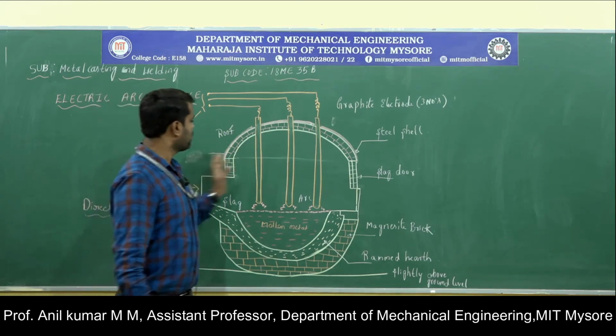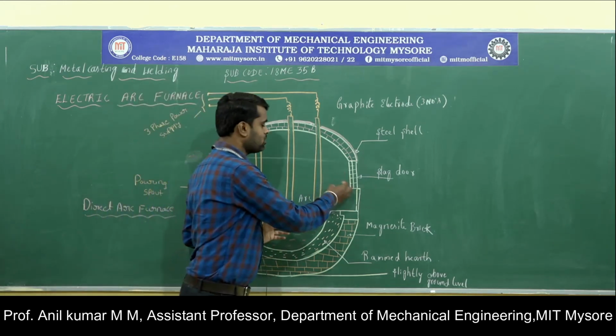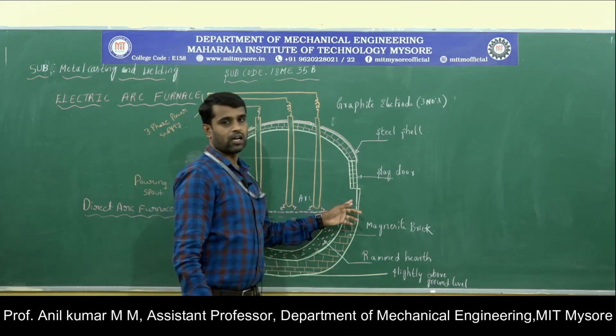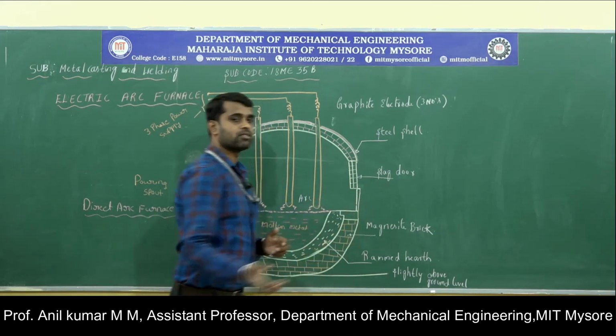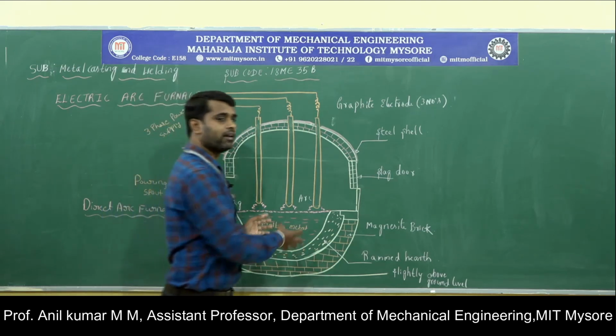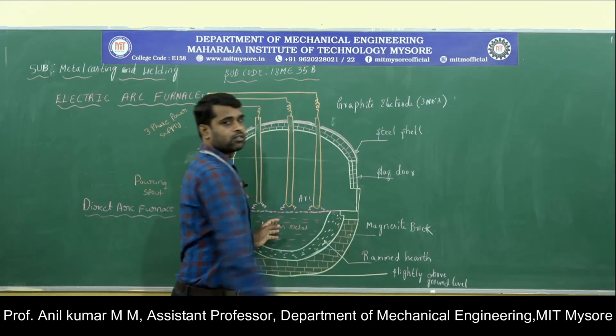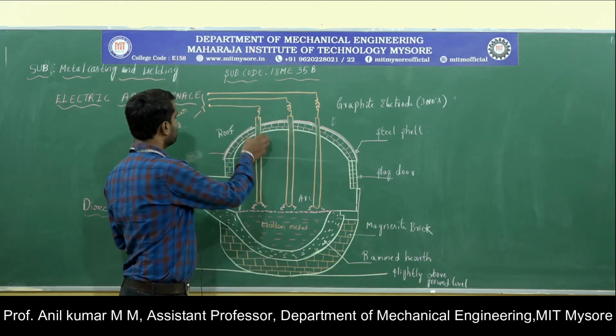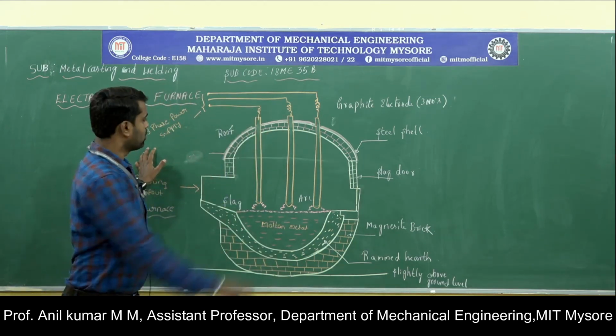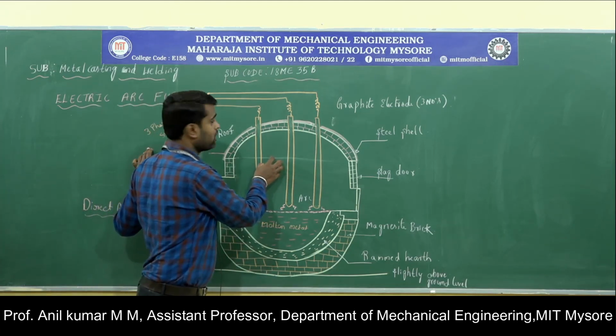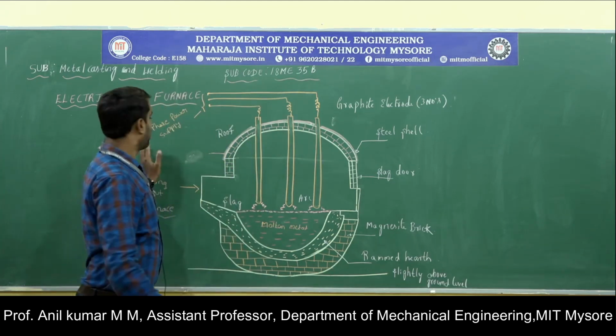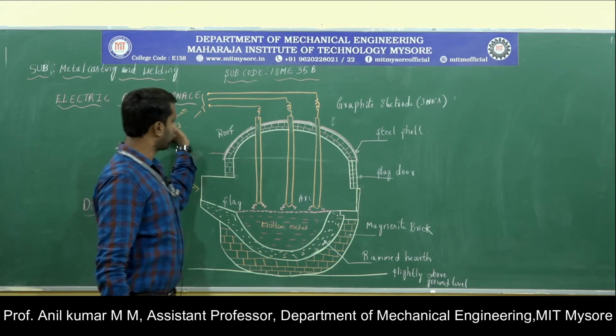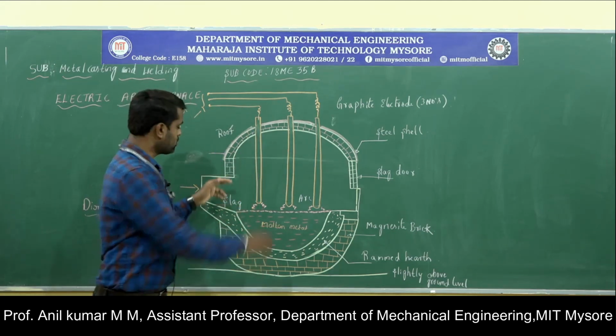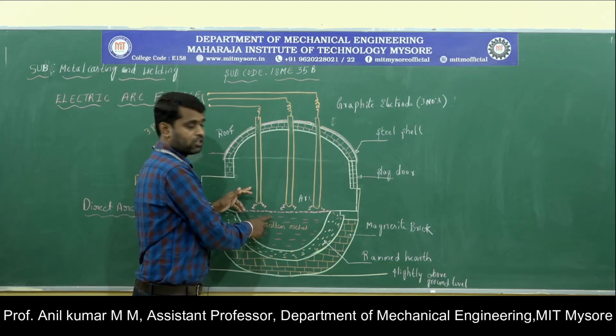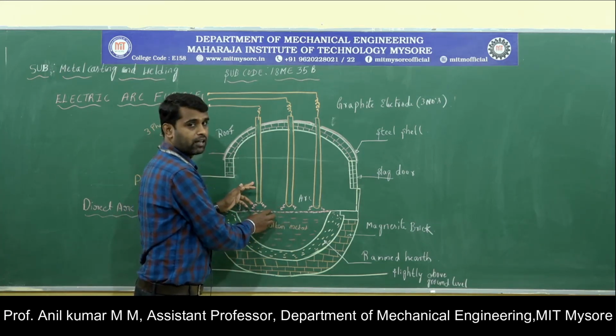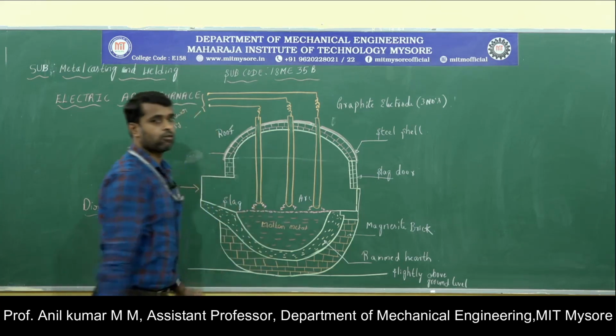Okay, next, in the working, initially we can add the charge inside the furnace through the charging door. We can add the charge, either steel scrap or cast iron, inside the furnace through the charging door. Next, these electrodes can be connected to the power source. The 3 non-consumable graphite electrodes can be connected to the power source, and the suitable current and voltage can be supplied through the electrodes. These electrodes initially contact the metal charge which is placed inside the crucible and then separate, and then in that gap the electric arc will be generated.